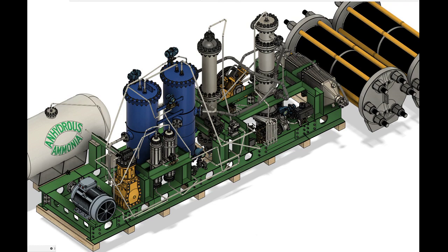Steam methane reformer capex. Steam methane reformer technology, much like alkaline electrolysis, is dependent to a large extent on the market price of alloys with a high nickel fraction. These include Inconel, Incoloy, Hastelloy, and stainless steel, to name just a few. Steam methane reformers may operate as high as 1000 degrees Celsius, and use nickel-based catalysts usually supported on alumina. HK40, comprised of 22% nickel, is the industry standard alloy for reformer tubes.